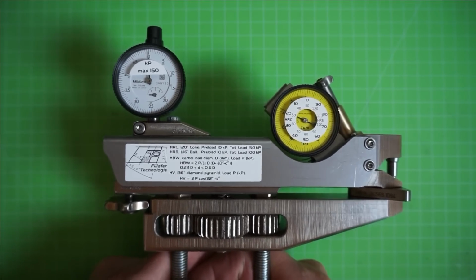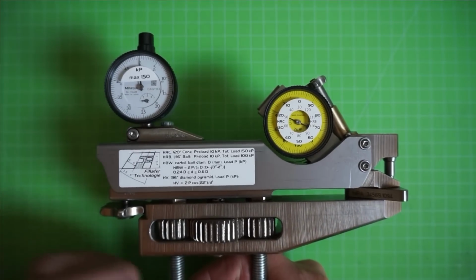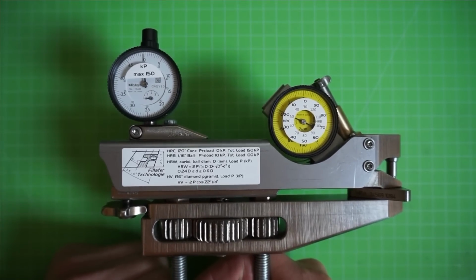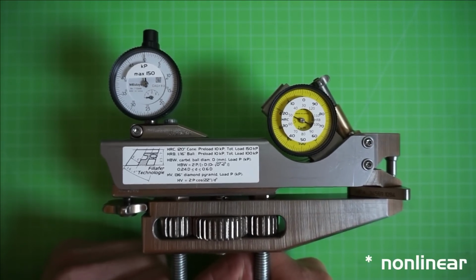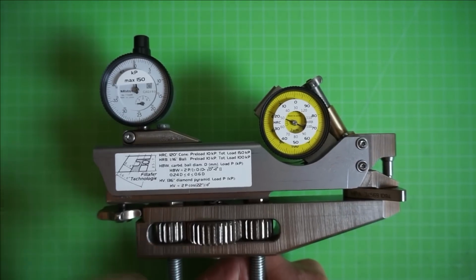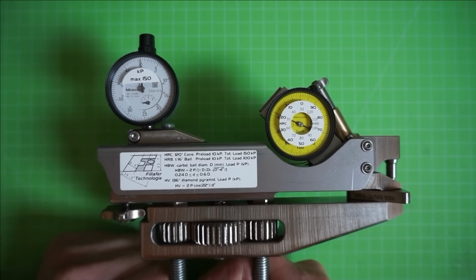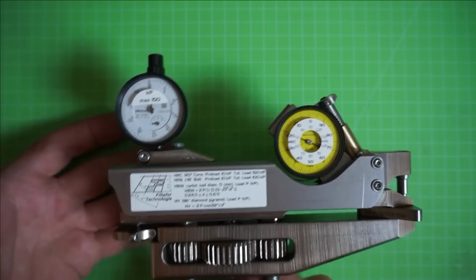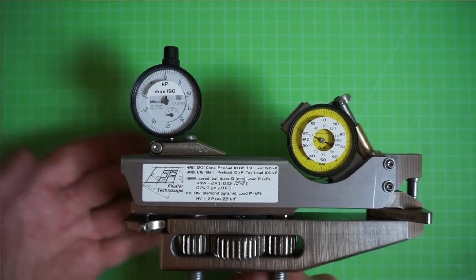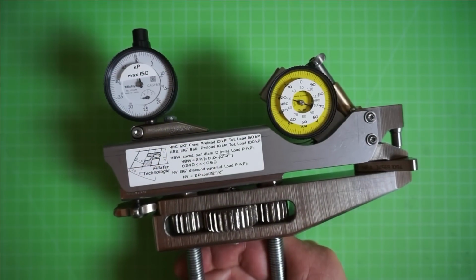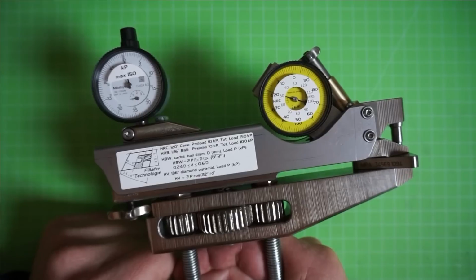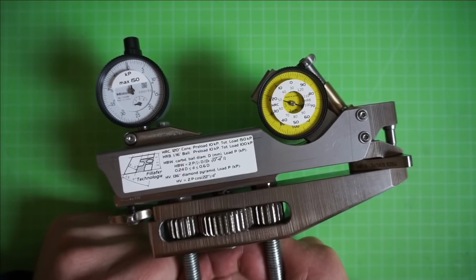That's the nice thing, because this is quite related to material strength and not as linear as Rockwell. So with different loads we should achieve the same result for the hardness. So let's see about that. Let's use 50 kiloponds of load. Good practice in hardness testing is to always use the largest load that you can.